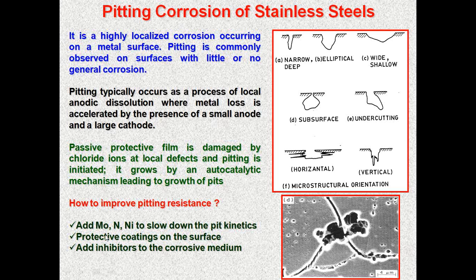So there are methods. By modifying the alloying elements, adding certain elements like molybdenum, nitrogen and nickel, you can slow down the pit growth. Or you can have some protective coatings on the surface which will avoid the pit to start, or you can add inhibitors to the medium that will stop the chlorides and other pitting agents from attacking.